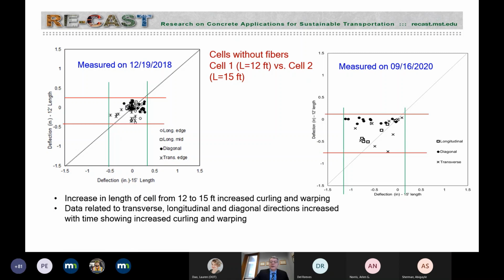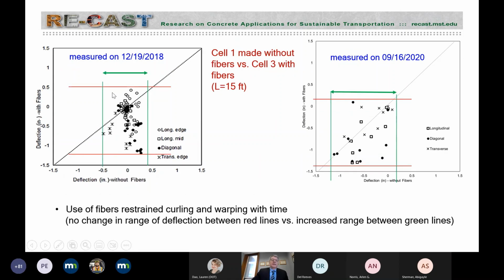Neither of them has any fibers. And then this next slide compares cells number 1 and 3. Cell number 3 is made with fibers, and both of them have the 15-foot lengths. And we could see that the deflection with fiber at initial age was much higher than that without fibers, same lengths. But the difference between them with age seems to be decreasing.